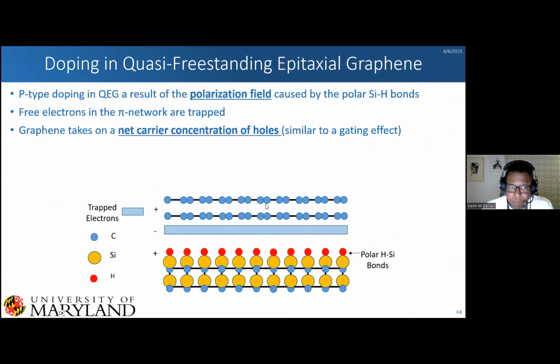And then the other explanation is this doping of our material. So we have a polarization field caused by our polar silicon hydrogen bonds. We have free electrons in our pi network. They are trapped here below our graphene. And this is why our graphene takes on this net carrier concentration of holes, very similar to gating. And so even though I said before we did not have a field effect transistor, we do have a field effect transistor. It just happens to be built into the material.